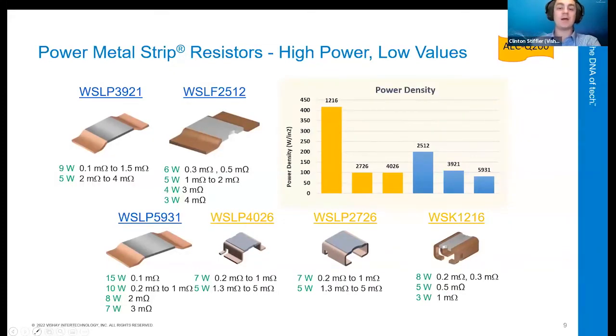They also provide high power ratings to eliminate the need for parallel resistance elements, which can lead to measurement error caused by current flow in the measurement circuit due to small differences between the resistance elements when you're dealing with these low values. So these current sense resistors have demonstrated reliability for the broad range of demanding conditions defined by the AEC Q200 out to 2,000 hours or cycles, not the typical 1,000 hours or cycles. This is the reason that they're being designed in by the biggest names in the automotive electronics industry for the conversion to electrical systems and EV hybrid systems.